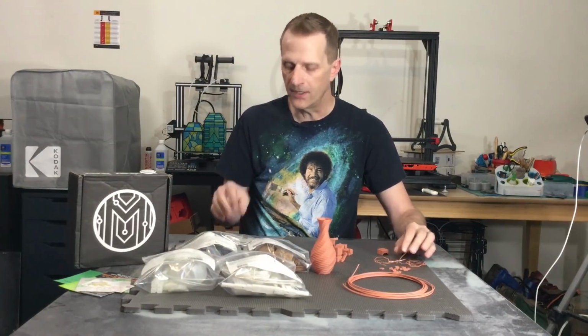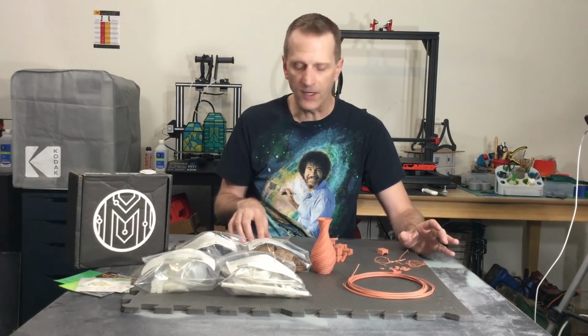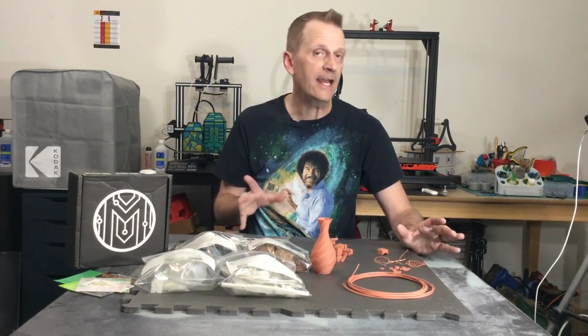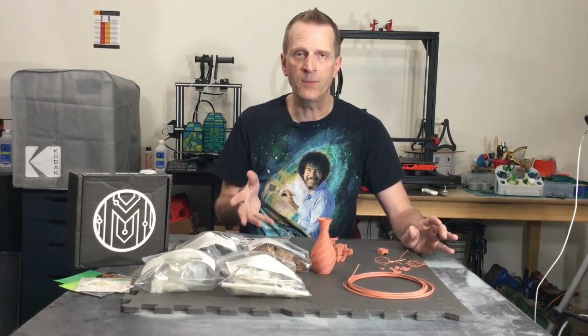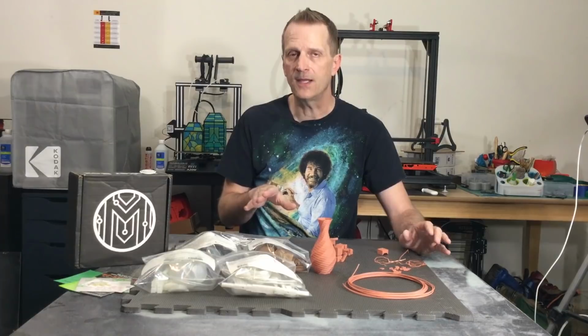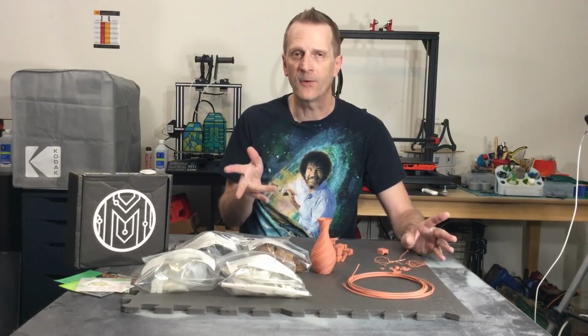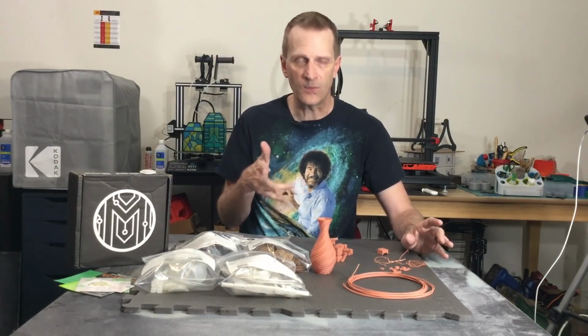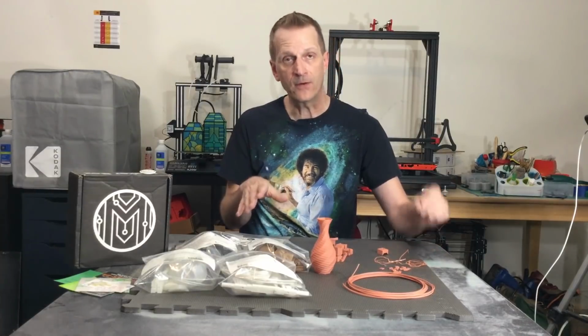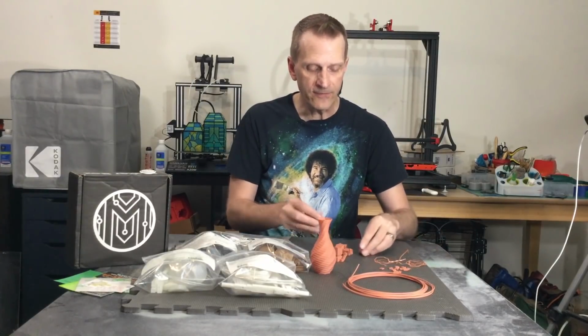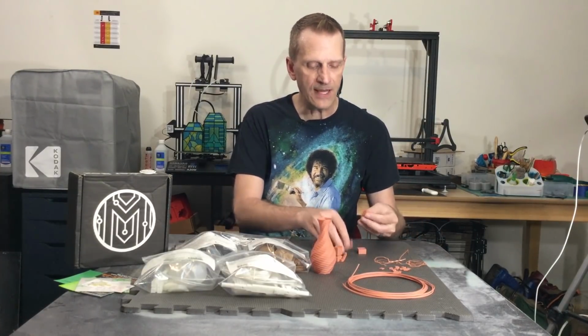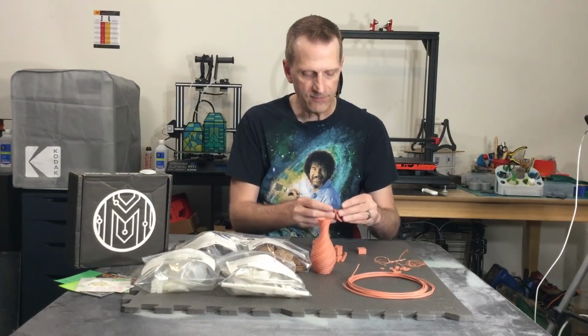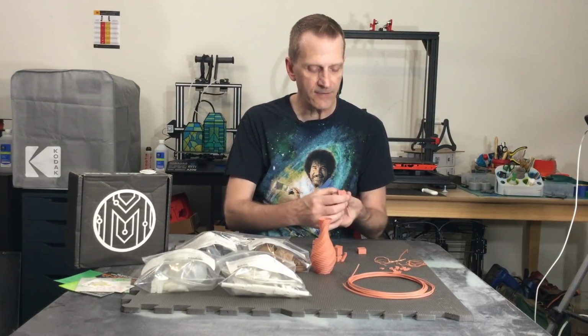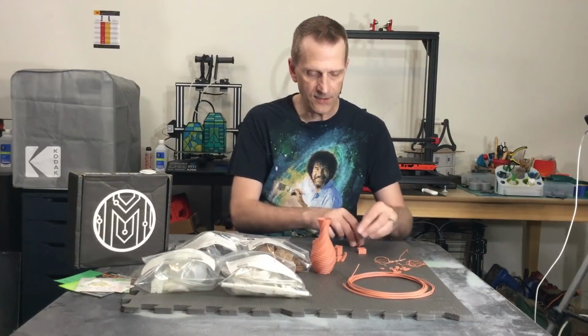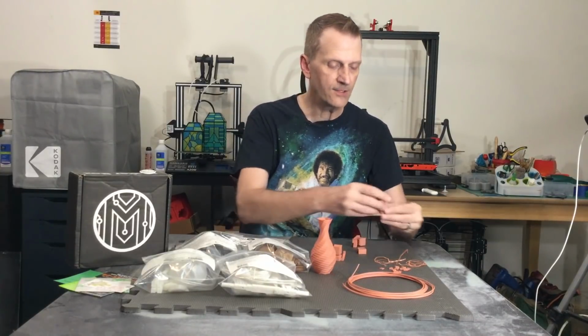So we went ahead and started with, still at 220 degrees C on the hot end, 85 on the heated bed for the G-Max. All the same settings, except for now I slowed it down. I was printing at 40 millimeters per second. I was seeing some bed adhesion problems, so I dropped it down to 35 millimeters per second. So the first print that came out, while it printed out successful, I have quite a few of them here that have fallen apart, I was seeing something I'd never seen before. Now, I don't know if you'll be able to see it on this one. You'll be able to see it on this one.